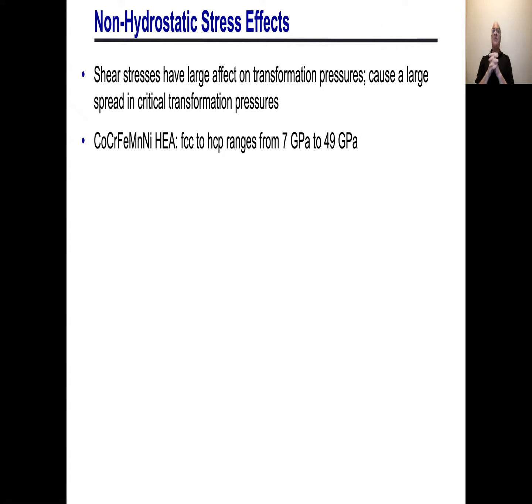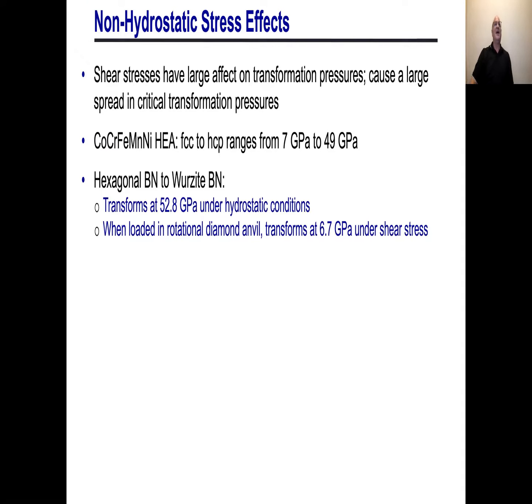And if I look at some examples, here's a high entropy alloy. I figured I'd start with something recent. In this particular alloy, the transformation pressure from FCC to hexagonal close pack goes between 7 and 50 GPa. That's a very big range. If I go to boron nitride, under hydrostatic conditions you get a transformation at about 53 GPa. On the other hand, if you do it in one of these rotational or torsional diamond anvil cells, it goes down by a factor of 8 or so. Okay, so these are big effects.